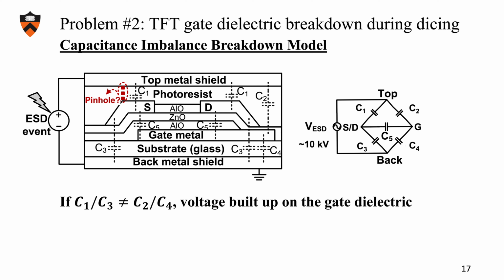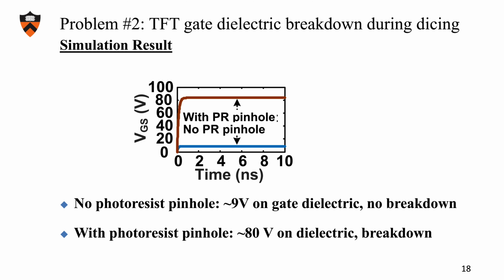Then, with these simulations, we found that if there is no pinhole in the photoresist, there will be about 9 volts built up on the gate dielectric, not enough for it to break down. However, if there is a photoresist pinhole, about 80 volts will be developed, far enough for breakdown.